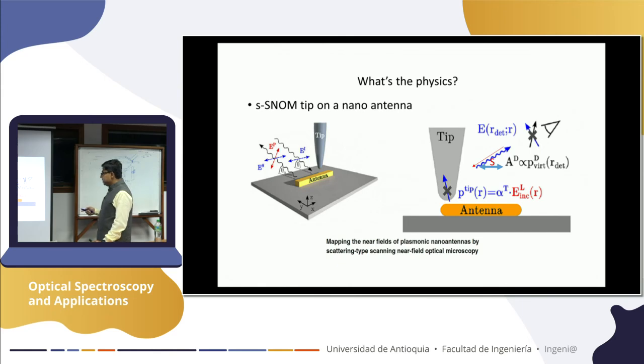It is very basic electromagnetism, that you're polarizing the tip with the incident field with the polarizability of the tip. So you choose the metal and the dimension that will determine how much it will be polarized. Each time you are creating charge oscillation, you are re-radiating the photon back. So you are actually re-radiating only from this near field.